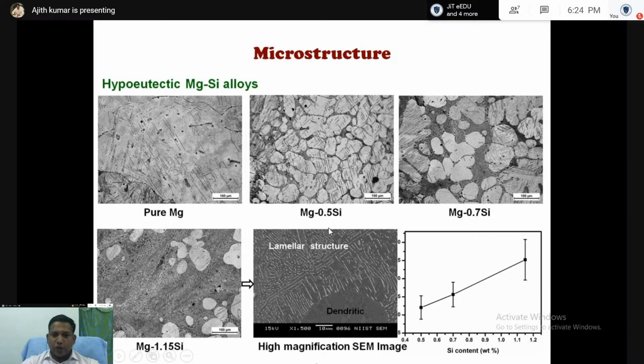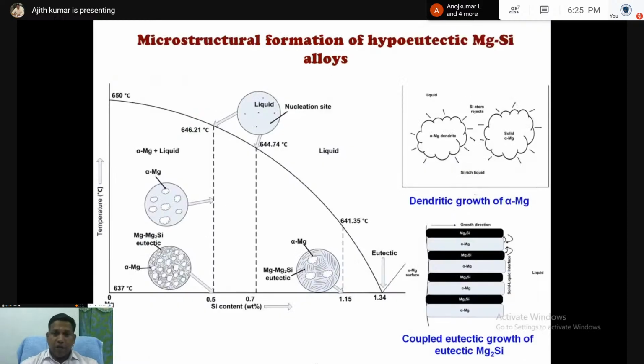Then we analyzed using SEM analysis. You see, this gray region is a lamellar kind of structure. It's like needle kind of structures are there. This is the lamellar spacing. We analyzed that. So from the high magnification system, we can understand how the eutectic phase is formed. After that, we understand how the microstructure is forming during solidification.